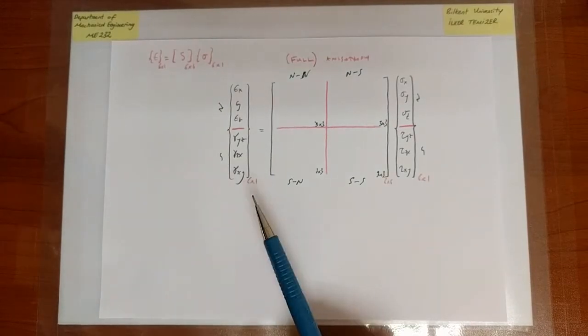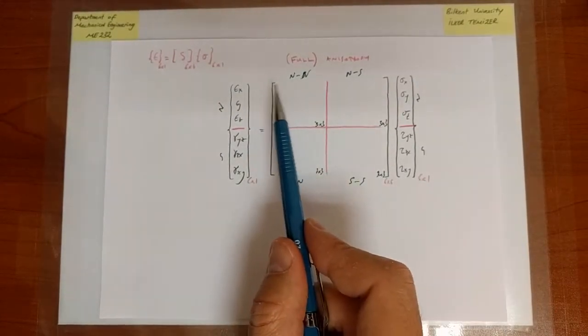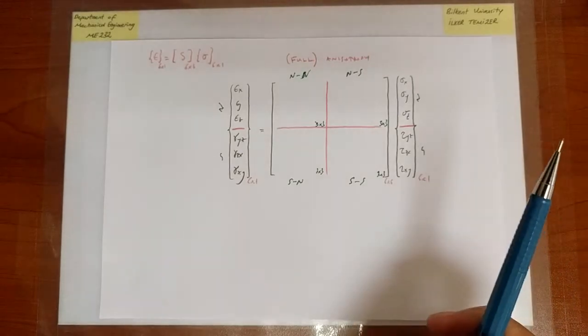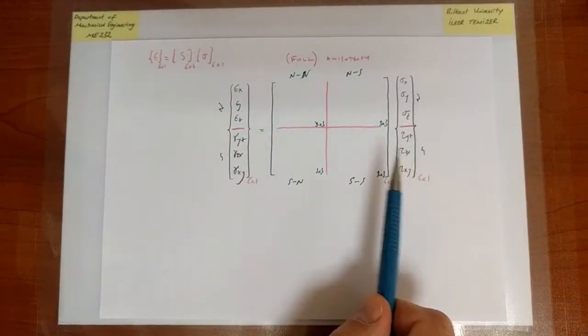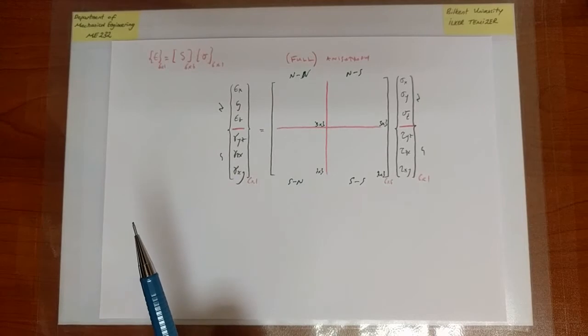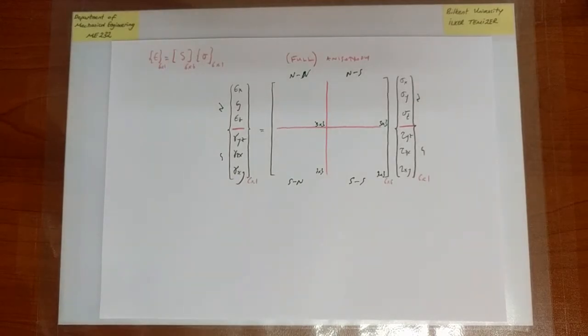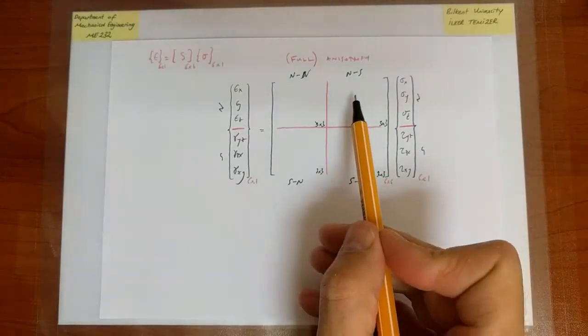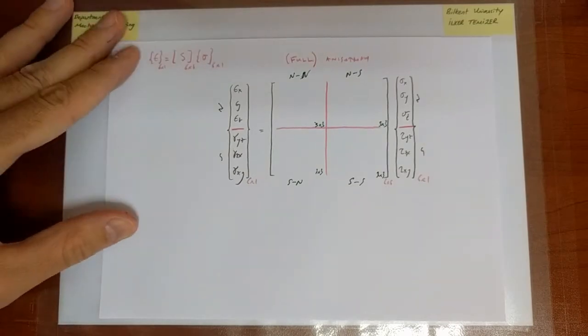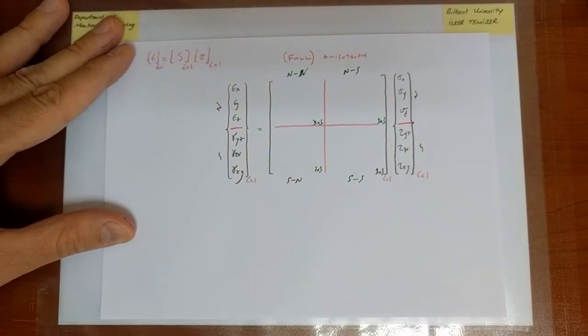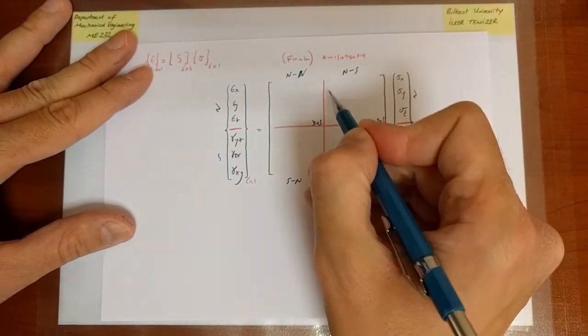So now I want to write the relation between stress and strain in its most general form. And in this most general form, I'm going to discard the notion that only normal stresses influence normal strains and only shear stresses influence shear strains. Which means that I should probably not think of these components as being zero. They do not have to be equal to zero. They can actually be anything. So these won't be zero.